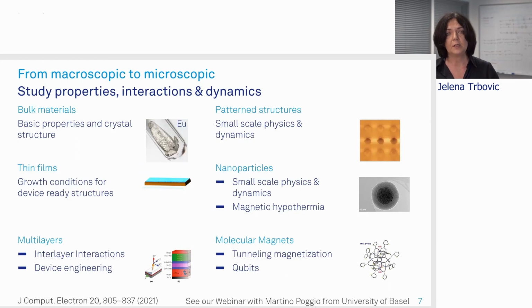So when we start with a characterization process, what we do first, we start from the bulk material. Here you can see a big chunk of europium that one can take and put in the VSM system and measure its magnetization. We can check if there's any magnetic anisotropy by turning the magnetic field with respect to a certain axis. And then once we think that the material is clean, we can then evaporate and grow nice thin film structures that are then ready for further device preparation.